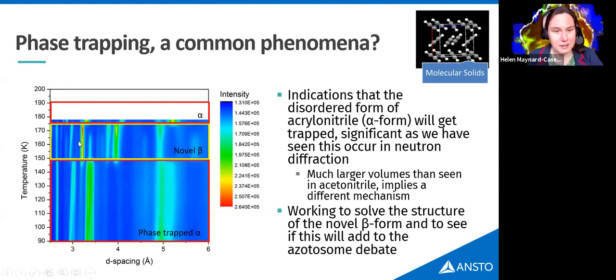So I actually think that this beta form, so we've started naming it, this alpha form is that same disordered high temperature form. We've discovered this beta form, which I believe is the low temperature form, but the awkward thing is we get the alpha form forming at the low temperatures as well. And the interesting thing is this has happened in our neutron diffraction data. So this is a much bigger sample.